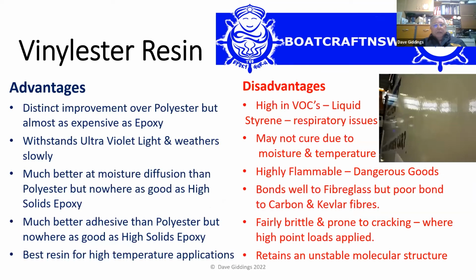Vinyl ester, again, it's a crossbreed between epoxy and polyester. Its biggest problem is it's an unstable resin. And if you have a look in the photo on the screen, that's a modern caravan skin. They do a lot of caravans these days in vinyl ester resin, but you can see the weave through it. It readily shows up the weave, and that'll change depending on the environment it's in. So that's one of its major problems. It's a lot more user-friendly than polyester when it comes to making composites, but it's still got its limitations.